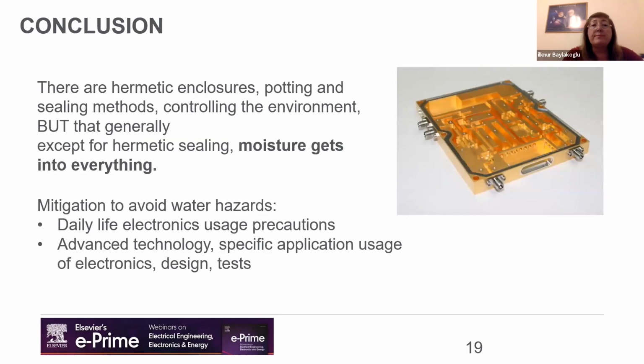As a conclusion, there are several failure modes and mechanisms related to the form of water in electronics, as we see. And as we mentioned, water film may connect conductors and result in leakage current, and material degradation can happen by absorbing water, especially for plastic parts. And also it can cause swelling of hygroscopic polymers and cause degradation. And there can be galvanic and creep corrosion, and there can be electrochemical migration. The moisture between biased metals causes metal ions to migrate. So there are several issues that can happen.